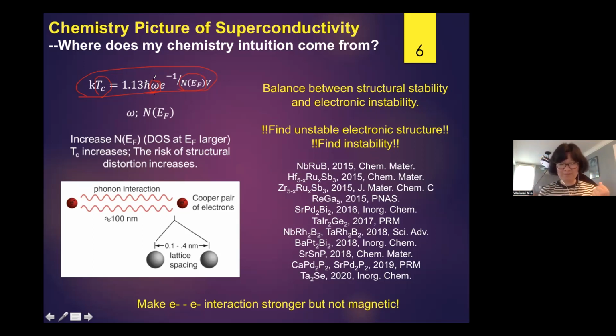For example, lanthanum hydrogen, okay? Hydrogen is very light, lanthanum is very heavy. So that's one way. And if we make ambient pressure compounds, we can try to put boron into the system. And you can see here, I love to use boron, because once you use boron, the TC can go higher. And here also the boron stuff.